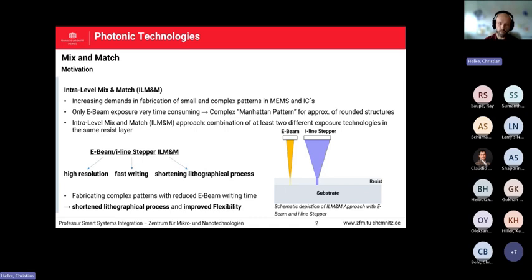One can also do it in one resist layer, meaning writing with the E-beam tool and, for example, another lithography tool in the same resist layer. As one can see here, the E-beam, the yellow one, writes really small structures, and in our case, for example, an I-line stepper exposes the larger structures, both in the same resist layer. So one lithography mask is ready for the structure transfer of the whole pattern of a whole material over the whole wafer. So with this, you can deal with high resolution.